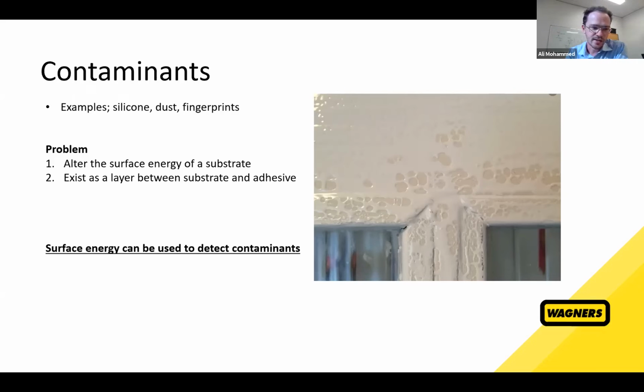But the good news is that surface energy, or measuring surface energy, can be used to detect these contaminants. If you have a surface that you know its surface energy, you've measured it, then you test again and find it to be different, you can more often than not assume that there is some sort of contaminant or there's something different about that surface. And you can look into why that is and what to do about it.